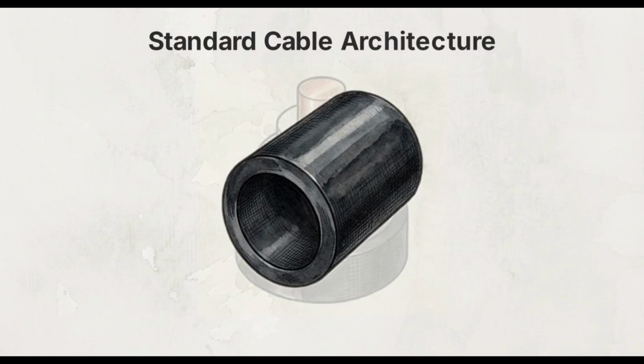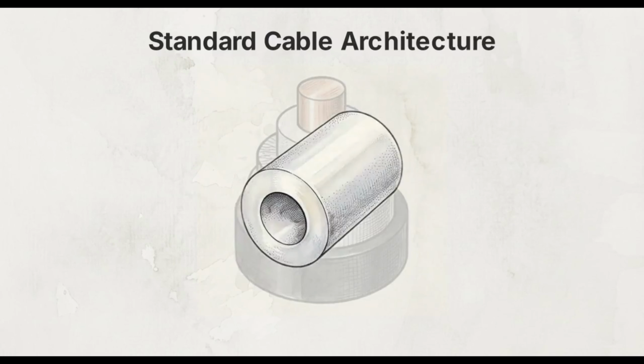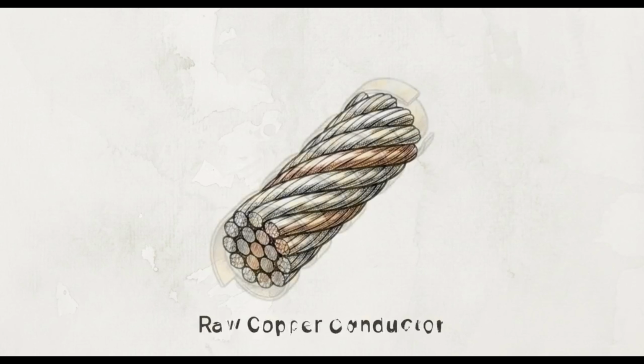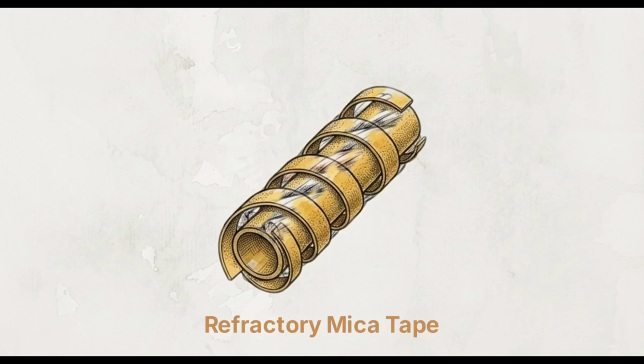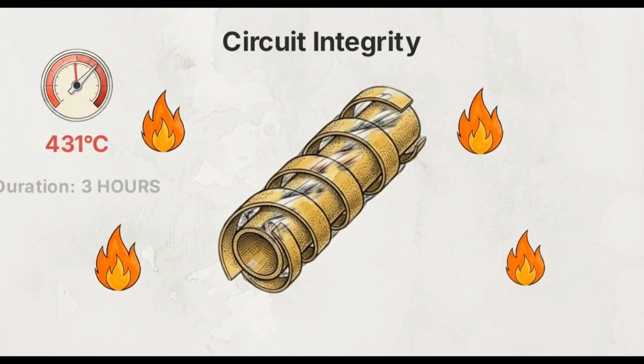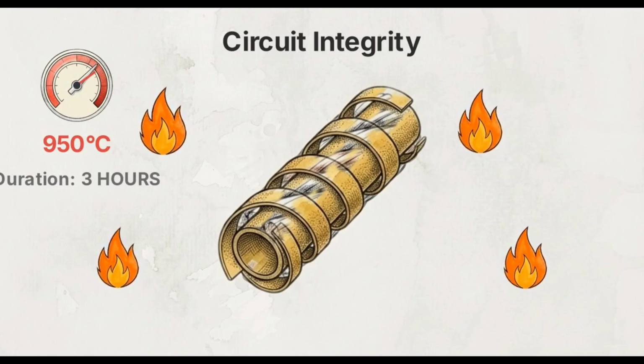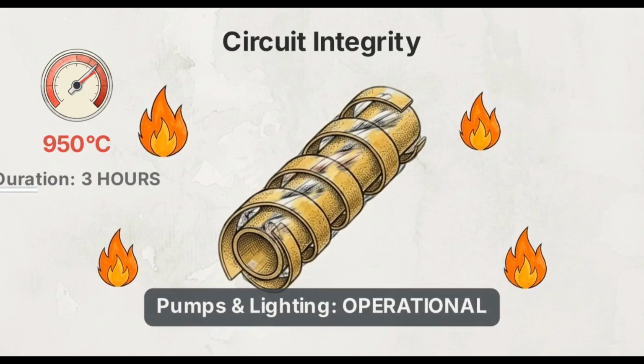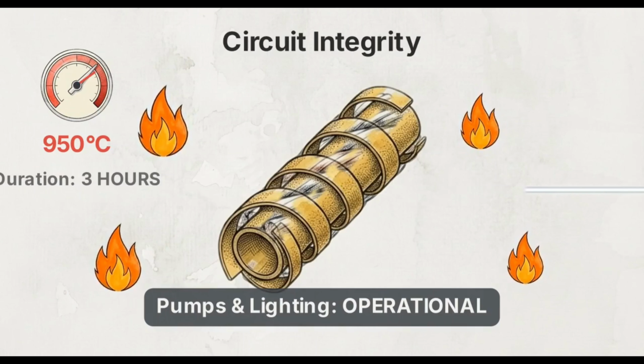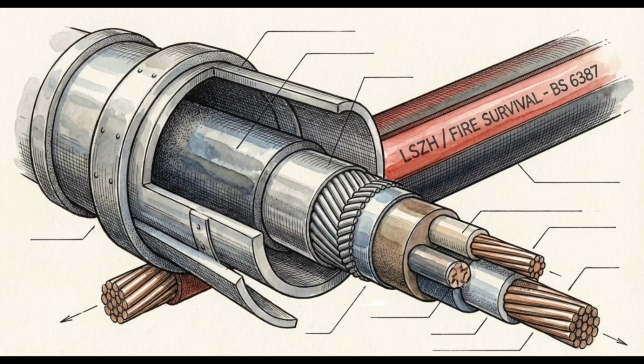This standard relies on a hidden mechanism, refractory mica tape wrapped directly around the raw copper conductor. This unyielding layer must maintain circuit integrity for 3 hours at 950 degrees Celsius, ensuring critical fire pumps and lighting remain operational while the building burns. Modern outer sheathing functions as a heavily regulated life safety technology built to satisfy the uncompromising requirements of global fire